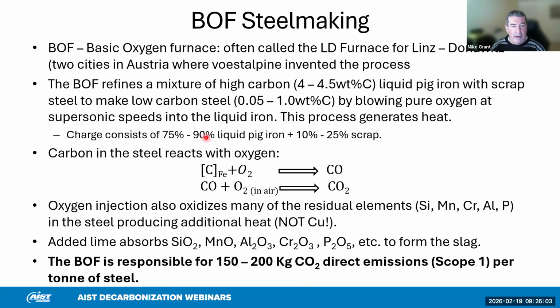So BOF steelmaking, classical example, this has been the primary way of making steel since the 50s. BOF is basic oxygen furnace, and in some parts of the world, like here in Europe, it's often called LD furnace, which stands for Linz-Donawitz, the two cities in Austria where Voestalpine invented the process. Basically, we're blowing in high velocity oxygen at supersonic speeds to refine a mixture of high carbon liquid metal from 4.5 weight% carbon down to between 0.05 weight% and 1 weight%. And we're blowing this down with oxygen.